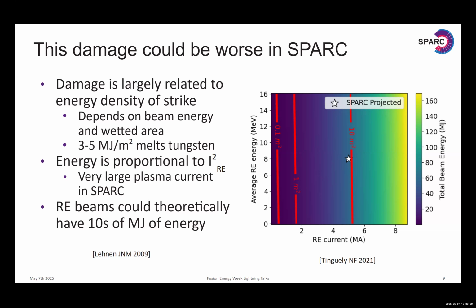So there is a threshold for which melting occurs, and that threshold is around 3 to 5 megajoules per meter squared for tungsten, which is going to be the first wall material in SPARC. And the energy that a runaway electron beam has is proportional to the current squared. This is why when we look forward to SPARC, which will have a plasma current of 8.7 megaamps, this starts to get quite concerning, because SPARC will have the highest plasma current of any device so far. That means that we could see really high energy runaway electron beams, up to tens of megajoules, which is very, very powerful.